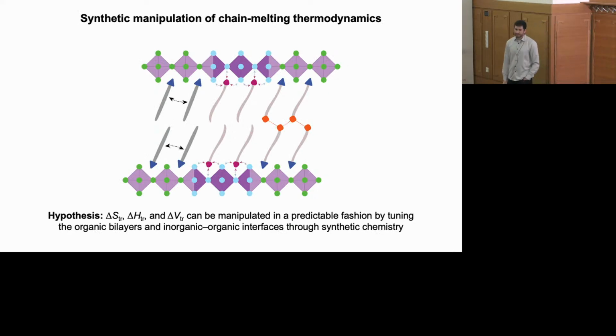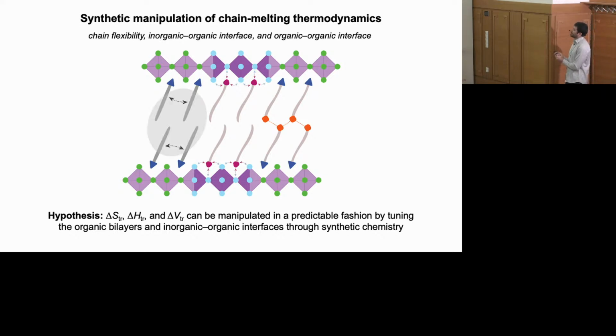And so this is one of the other reasons we were really excited about this particular class of materials, 2D perovskites, because of their tremendous tunability. Right? So we can think about making all kinds of modifications to the different components of these lattices to tune and optimize their phase change thermodynamics. So we can think about tuning the interactions between the organic layers within these 2D perovskites. We can think about tuning the interaction between the cationic head group of these alkyl-ammonium chains and the anionic pockets of the inorganic sheets, as well as the interactions at this organic-organic interface. You can think about functionalizing these organic molecules, swapping out different halides, different metal cations, and all kinds of things like that.